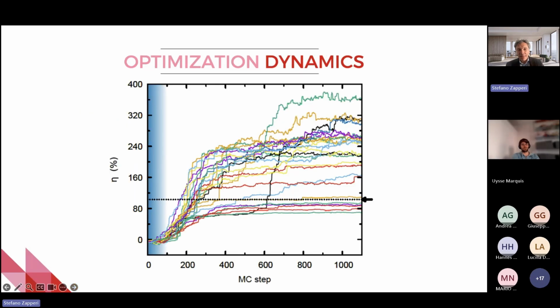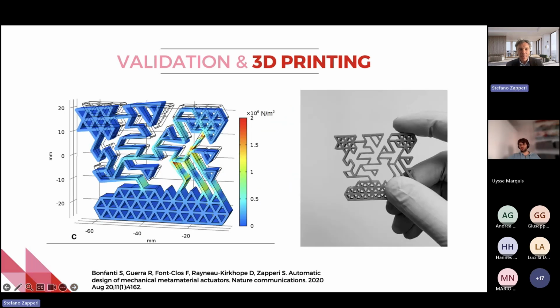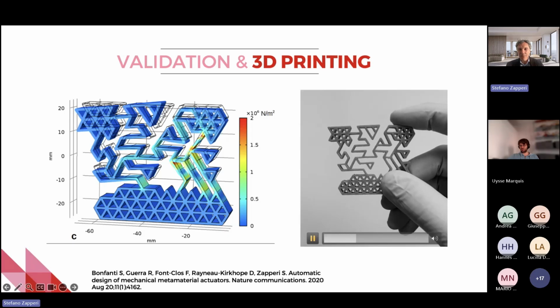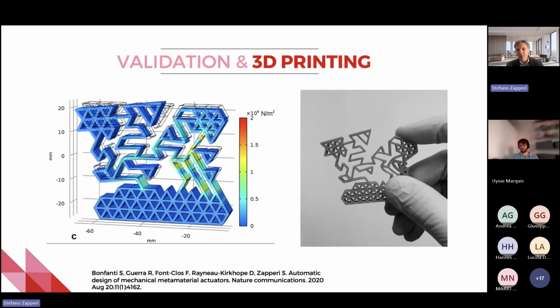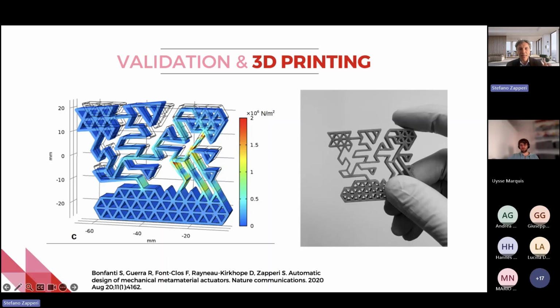And okay, these are the trajectories, so we can try different times and then see different stories. And for instance, at some point we get something that we like, this green line here, and a very high efficiency. And so we may want to take that one. Once we have it, we can for instance look at it and make some finite element simulation of it to see, for instance, that there are high stress regions. We may want to correct for that, but okay, that's another step. But then at the end, we can check if what we produced makes sense and whether it does the actuation that we programmed by 3D printing the structure. So this is a bit the plan, and we can do it for different type of things.